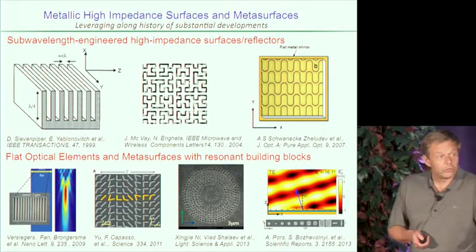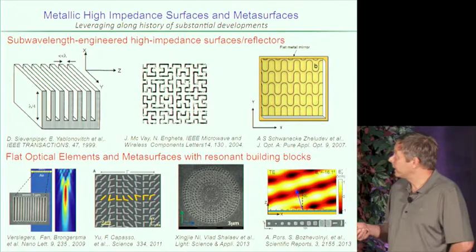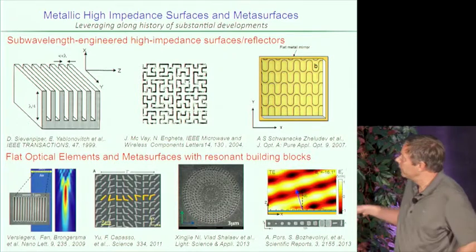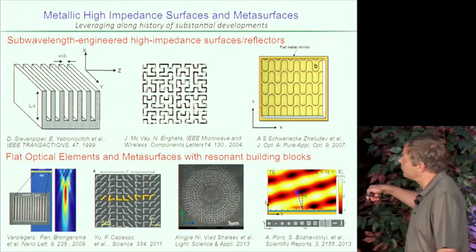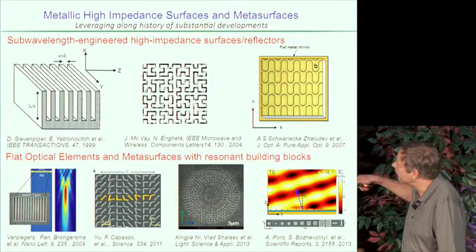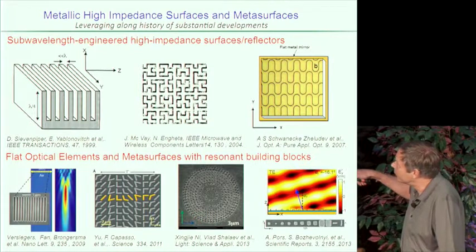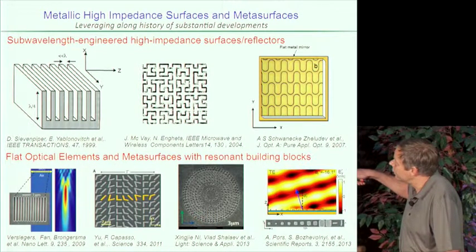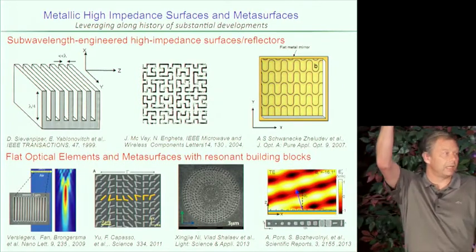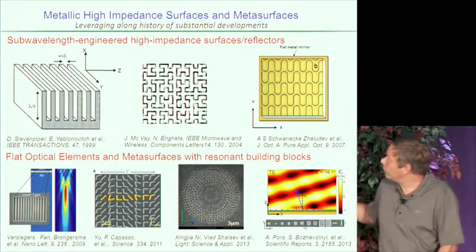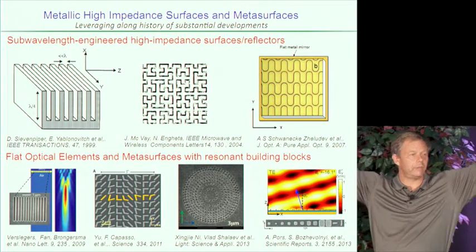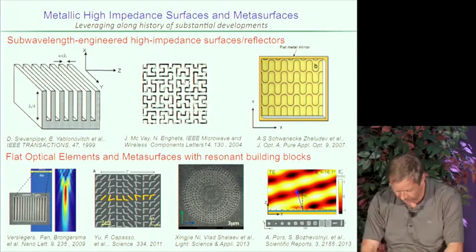And first, I want to acknowledge an enormous amount of work that has been done in the microwave regime on nanostructured metals and also semiconductors. Here's work from Eli Yablonovitch and Nader Engheta's group about a decade or so ago. People found that if you, for example, just dig an array of grooves into a metal film, where the size and spacing of the grooves is small compared to the wavelength of light, you can manipulate the reflection of light. And interestingly, if you have this distance be much smaller than the wavelength of light, you avoid first-order diffraction. The only thing the light can do is to come in and reflect.